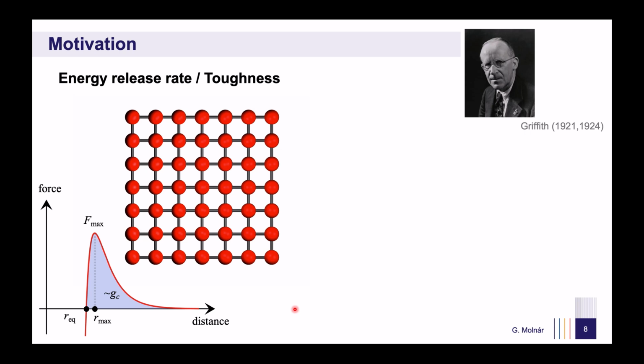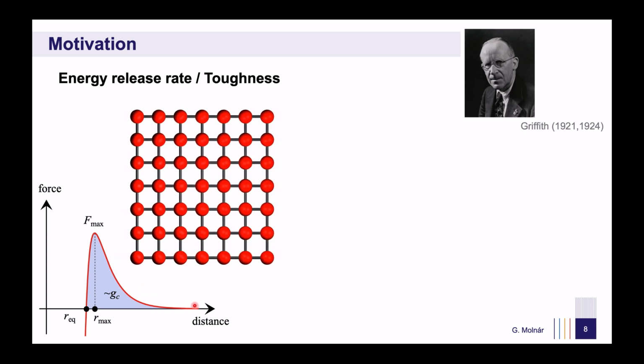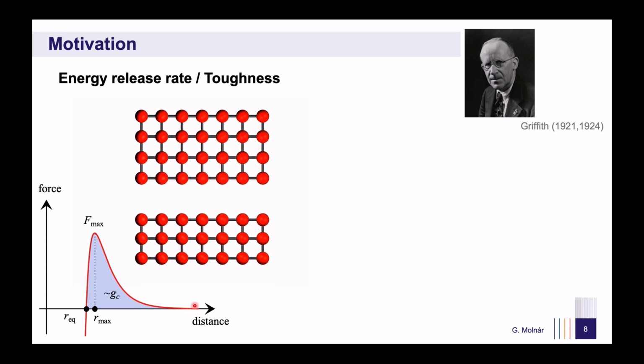To address this issue, in the 1920s, Arnold Griffith reformulated the conventional approach to material failure. Instead of just comparing stress and strength, he looked at atomic interactions. He noted that while the maximum force in an atomic bond can be linked to the strength of the material, the interaction does not simply end at the maximum force, it has a gradual decline. From this, Griffith proposed that forming a new crack surface requires a certain amount of stored energy to be released. He correlated this energy to the integral of the interatomic force.